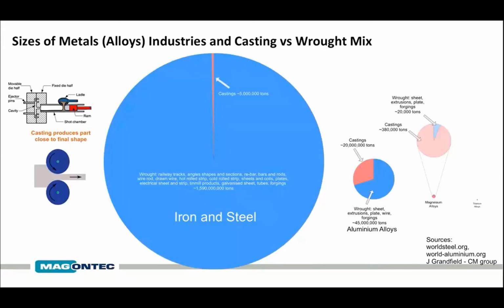component. You can see there's a very different mix. Iron steel is dominated by semi-finished products, with cast iron castings being relatively few. Aluminium is also dominated by wrought products, extrusion, sheet, but castings is a larger proportion. Whereas with magnesium alloys, it's the reverse. It's dominated by casting, with only very, very minor wrought applications.